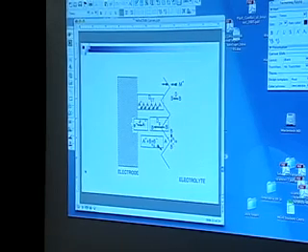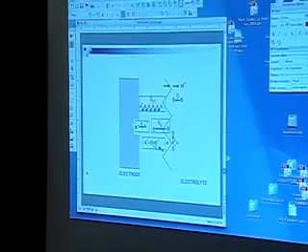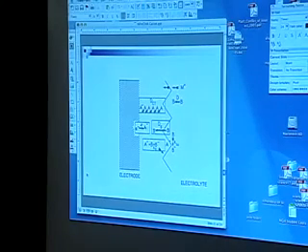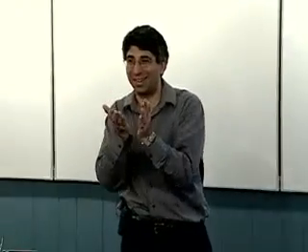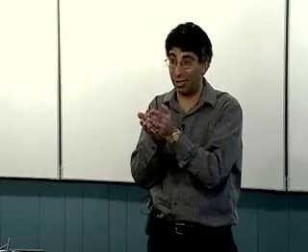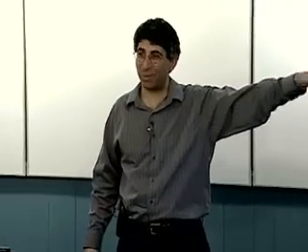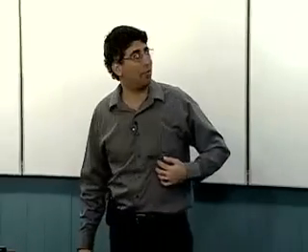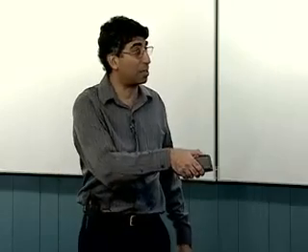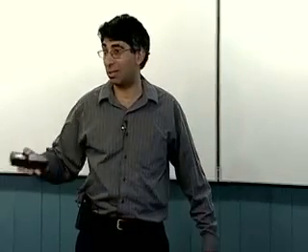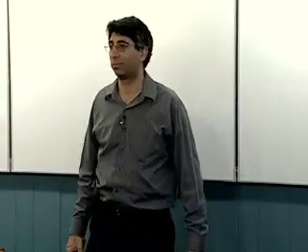Yeah. Well, it turns out there's always going to be an equation that holds that's 1 over the total current is equal to 1 over a sum of other currents. But they're different currents. In other words, there's an intercept. You can always extract an intercept, but what does that intercept physically respond to? Depending on what's rate limiting here, it responds to different things. And of course, if it had turned out it was something like the diffusion of B through the lattice or something like that, or even this process, we would not have got the Marcus dependence that we were looking for.